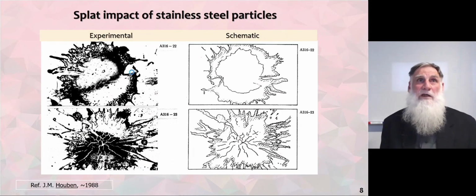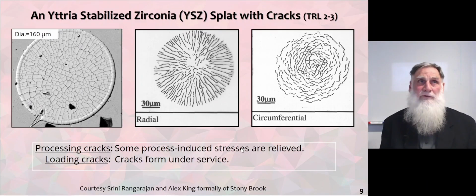So, for example, here is some work on splat impacts of stainless steel particles by Professor Houben in the Netherlands in 1988. His experimental work was translated into schematics that very clearly showed that depending on the thermal spray process conditions, these singular splats either had very smooth features, as shown by my pointer, or in certain conditions, they gave rise to a large number of cracks. So one of the major points is that the thermal spray process conditions give rise to different microstructural features.